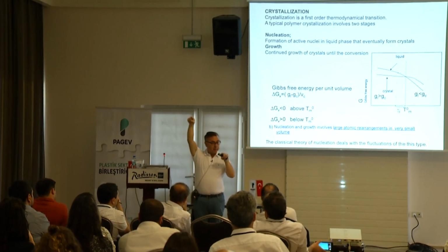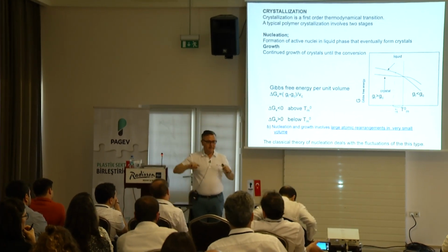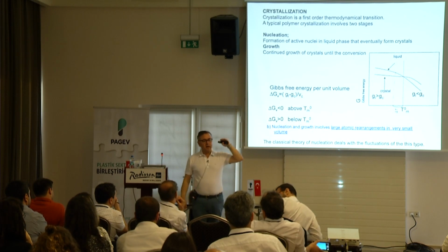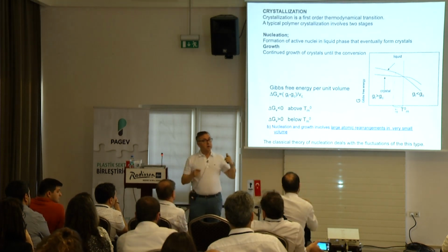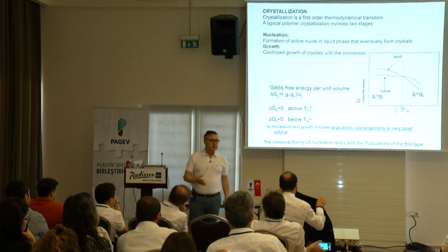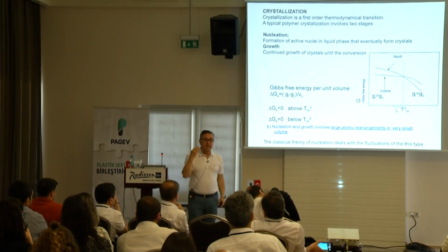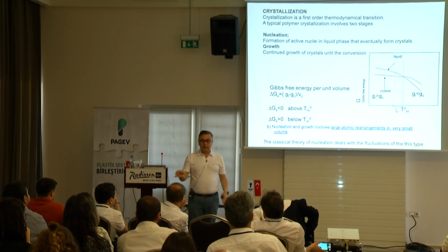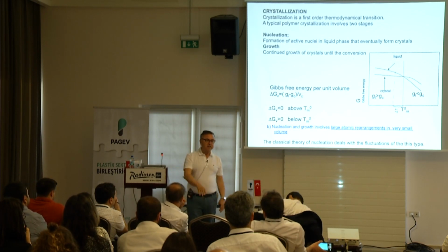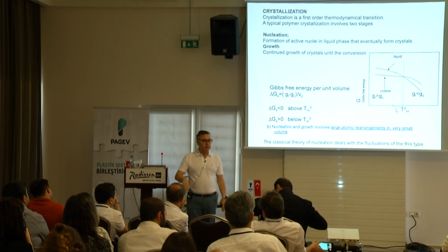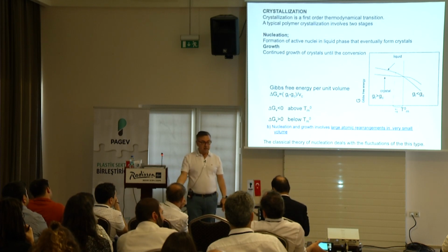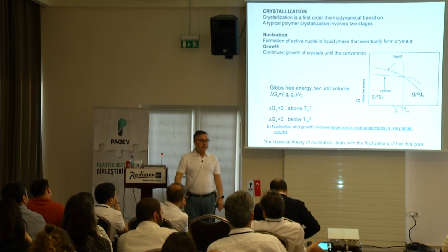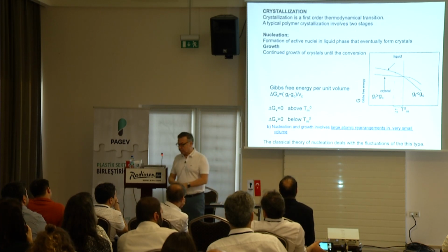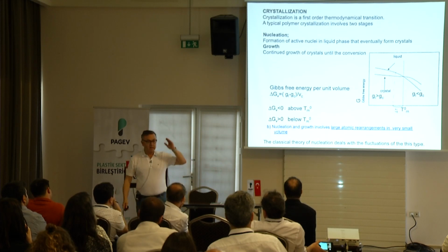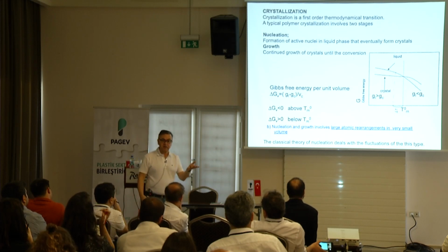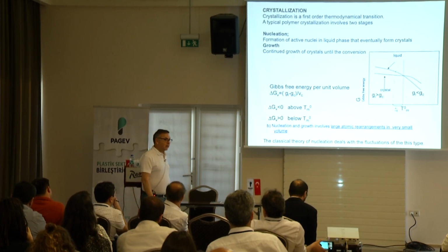So the material is metastable. It wants to go there. If you give it time, if you provide sufficient thermal energy, it wants to go in that direction. That's what metastability is. It's kinetically trapped. It's solidified and trapped, and 167 is for polypropylene. High-density polyethylene is 136, right? It's kinetically trapped. But if you look at the equilibrium melting temperature, it's much higher. For all of the polymers, the equilibrium melting temperature is much higher than what you normally measure on differential scanning calorimetry or whatever your melting technique may be.